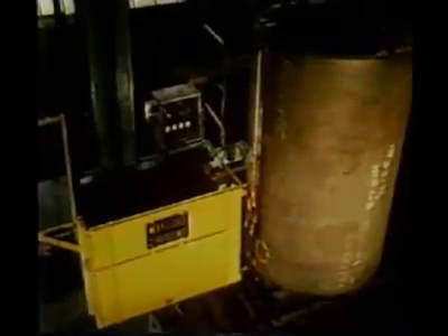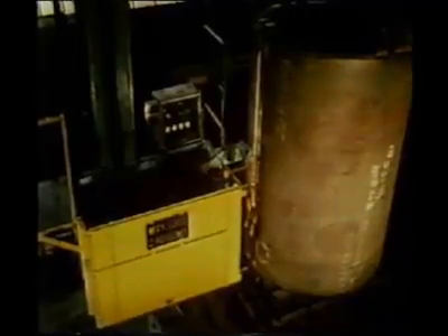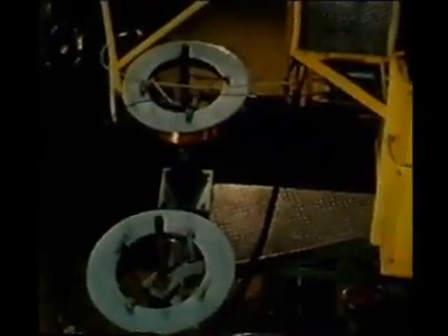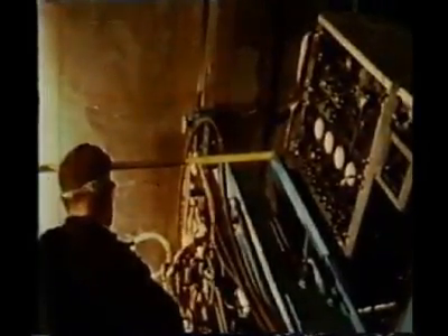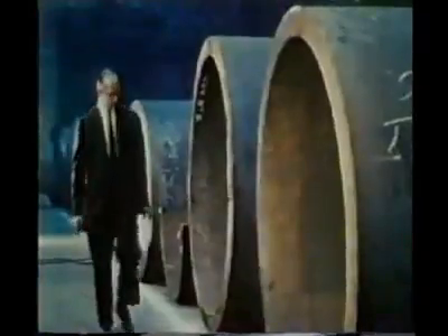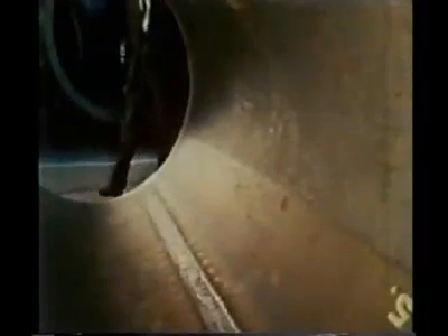Since we installed British Oxygen electro slag equipment here, our welding shop economics have been transformed. Now we can weld thick plate sections just as easily as the thinner plate. Because electro slag is a single pass system, the problem of turning over very large components, perhaps weighing several tons, is eliminated. Simplified plate edge preparation, fast overall welding times, and little or no afterwork to the weld, all these advantages add up to a much higher work output with greatly improved economy. We can now tackle at any one time a much wider range of work than ever before.